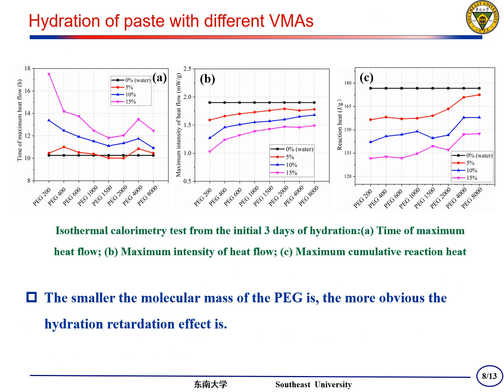And isothermal calorimetry test indicates that the smaller the molecular mass of the PEG is, the more obvious the hydration retardation effect is. The reason is that PEG has a double amount of hydroxyl of the amount of its own. PEG with smaller molecular mass has more molecules at the same mass, and correspondingly more hydroxyl groups. Hydroxyl easily forms hydrogen bonds with oxygen ions on the surface of anhydrous compounds, so PEG can be adsorbed on the surface of cement to retard cement hydration.